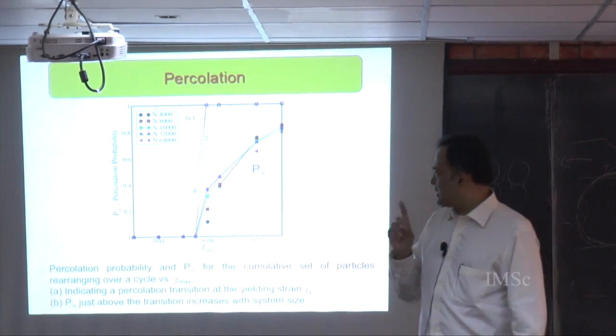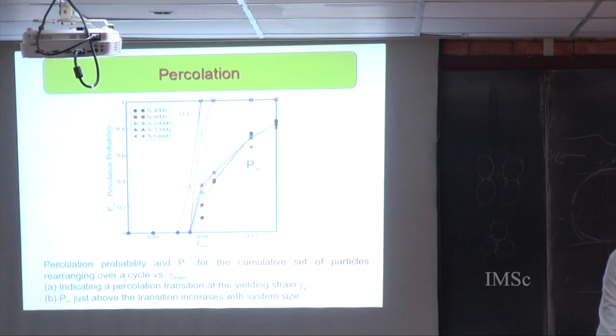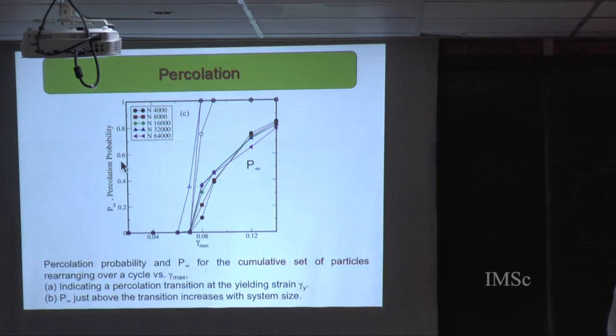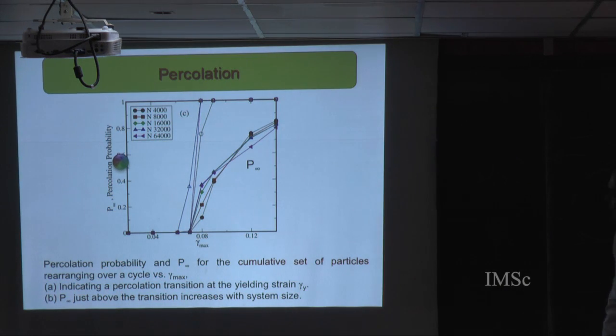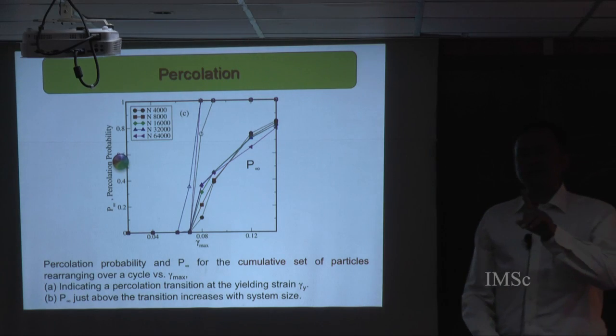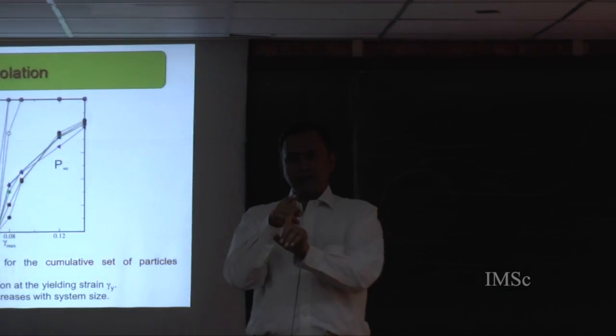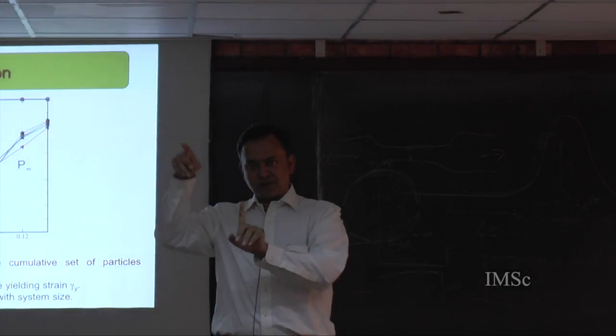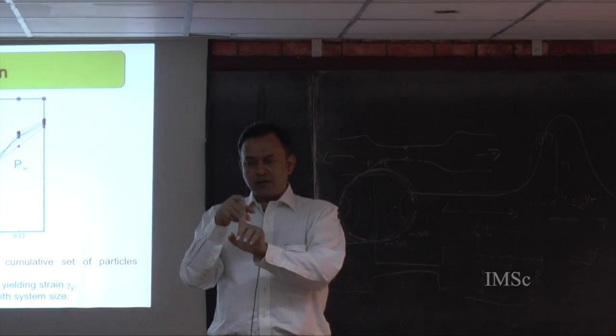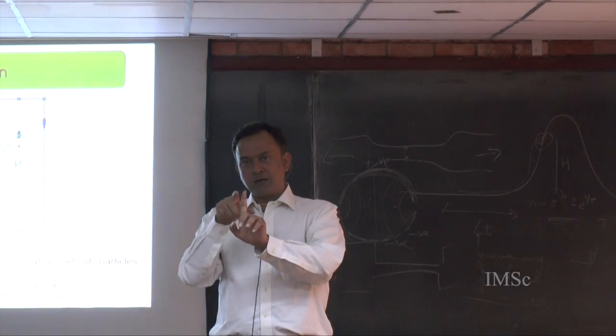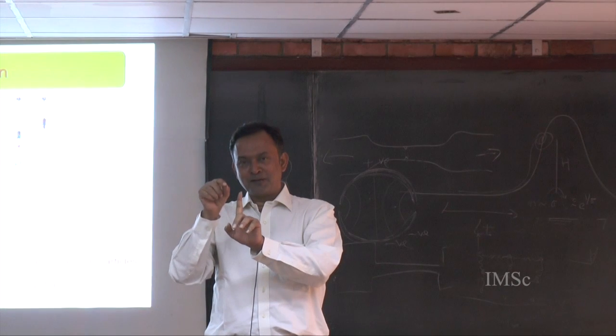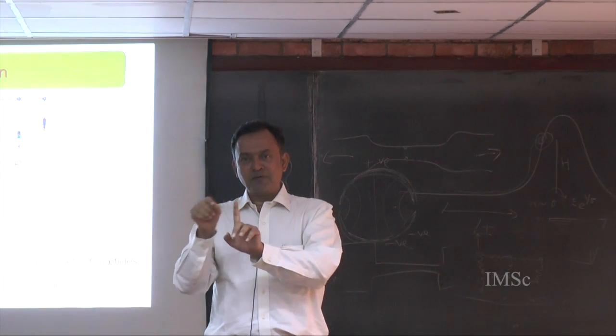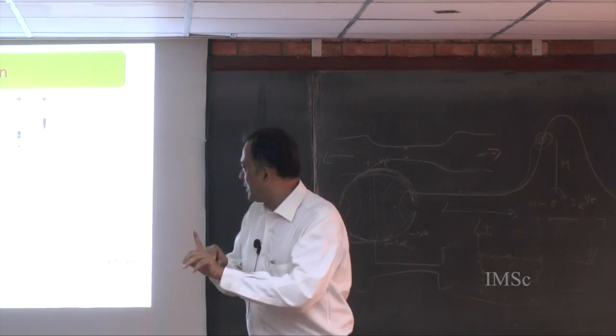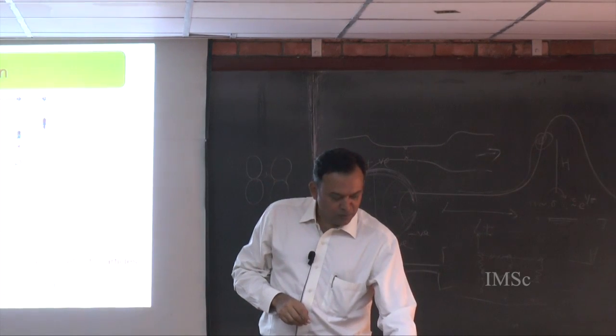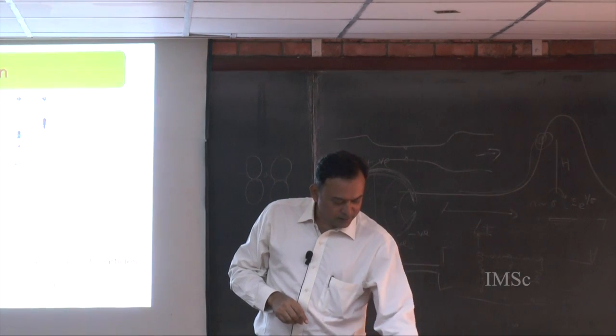But I showed you data which would answer your question, if I can get there. Because I had the data of the energies as a function of strain during the cycle, and you see that the zero strain value and the residual strain value are different of the energy, but they would still show a non-monotonic behavior if I can get there.